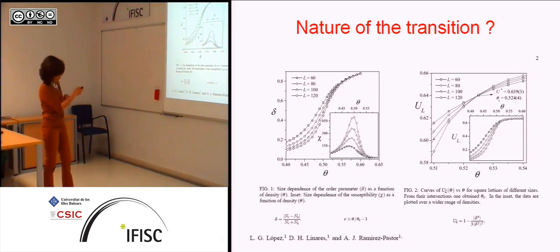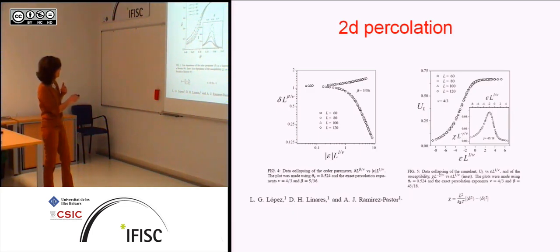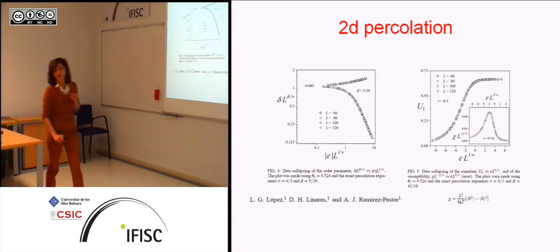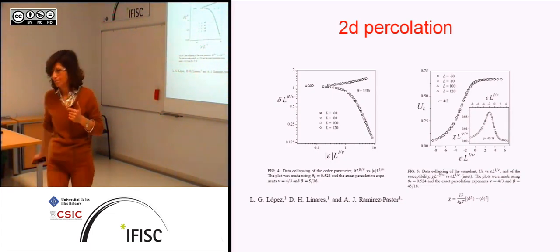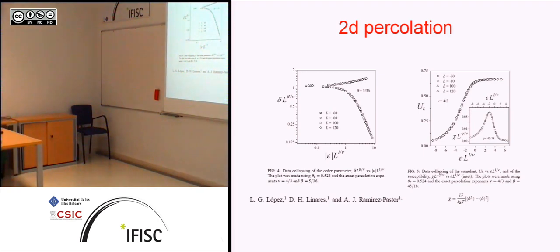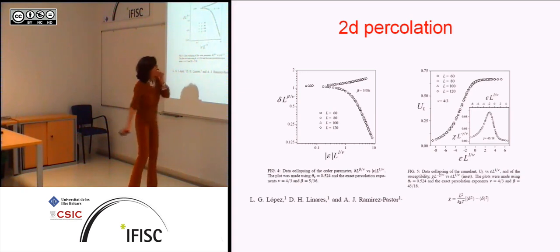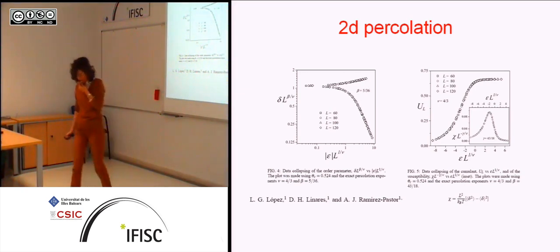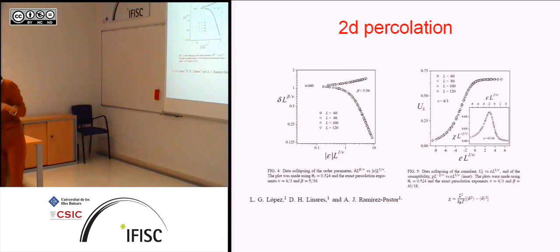For those of you who've done many of these things before, this is the Binder cumulant. This is actually the same order parameter that we defined before, just a different letter. This is from their paper, and the paper came out last December. And the exponents are from a two-dimensional calculation. And so the question to me immediately was, does this polydispersity, this equilibrium polydispersity, change the order of the transition? Is it the relevant parameter? Does it change the transition from Ising 2D to percolation?